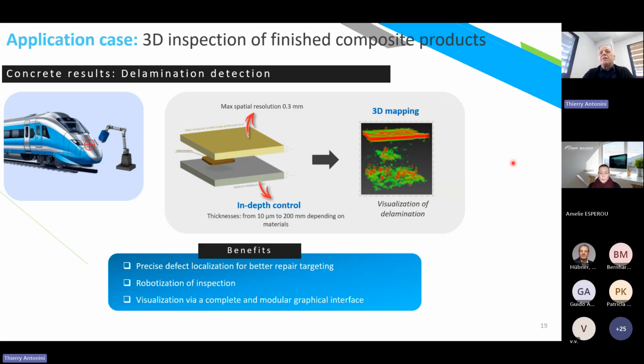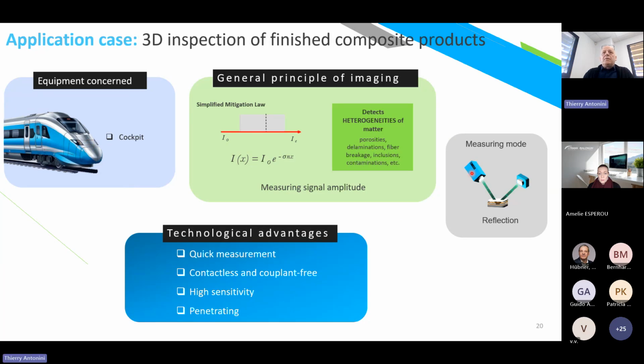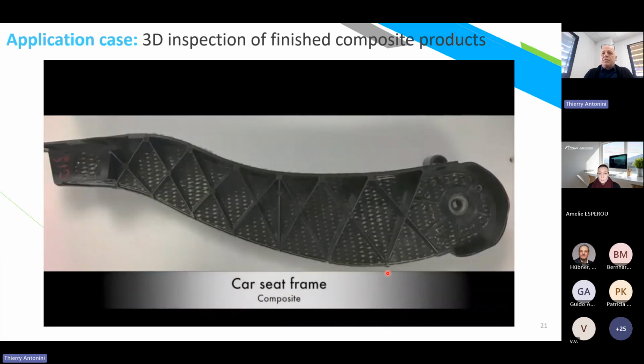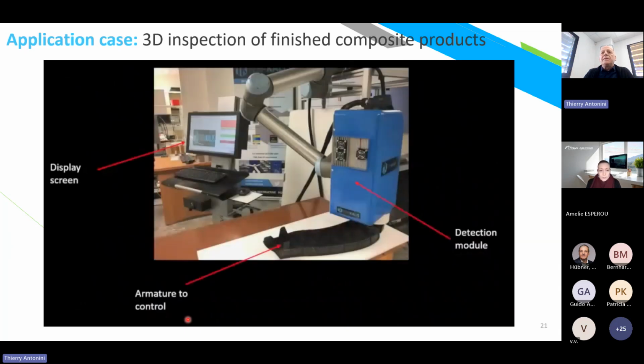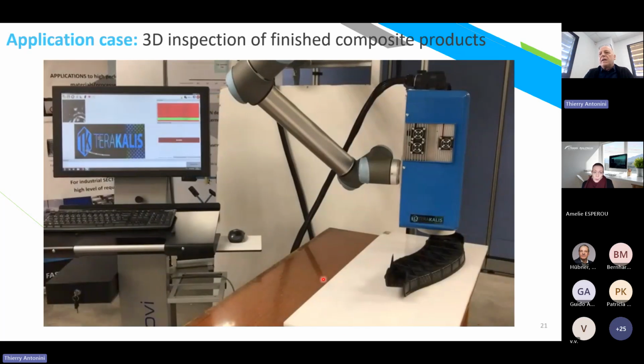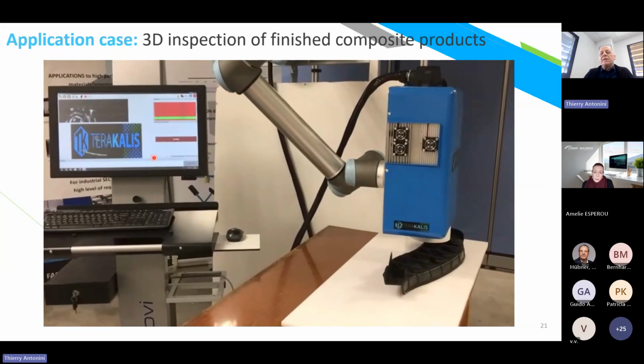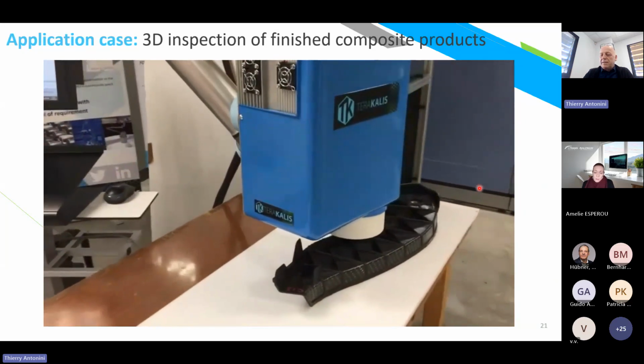Concerning a cockpit, for instance, you see what a THz image is, where we can detect, for instance, in this composite stack, a delamination that could be detected on a 3D mapping and located, and the size of the defect could also be provided by the system through our penetrating waves. Well, okay, I will go through due to time, but just for you to have an idea, this is a composite part that we can inspect. You see how it will be assembled, how the system could work, and the scan will start slowly, and in real time you can see some potential defects inside such materials.